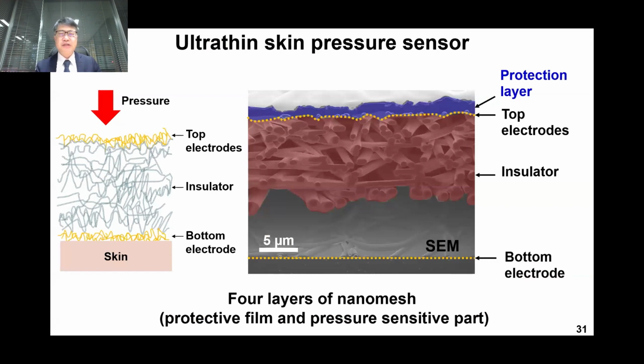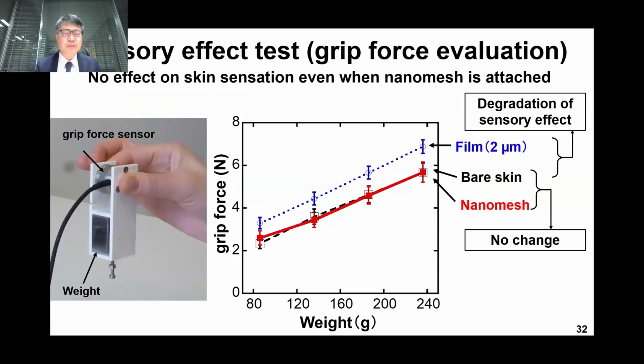Previous nanomesh sensors were a simple gold single layer, but now we make a capacitor structure by sandwiching the nanomesh insulator with nanomesh gold electrodes. Here you can see the nanomesh gold electrode and nanomesh insulator, and here is the bottom nanomesh gold electrode to form the capacitor structure. So when we apply pressure, the spacing between the two electrodes gets closer, and then the capacitance increases. So this is the sensing mechanism.